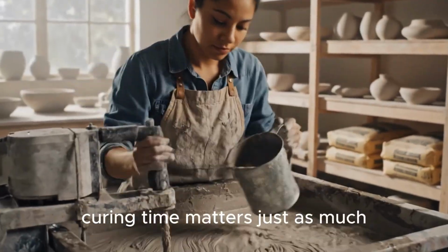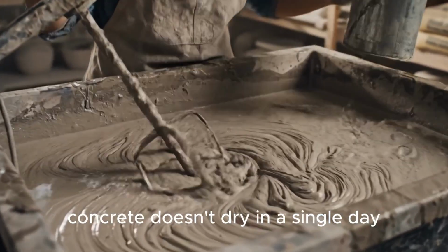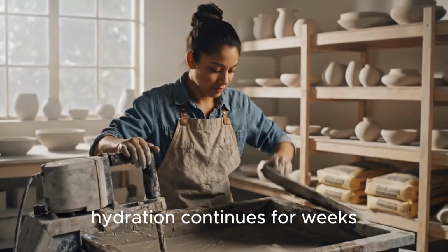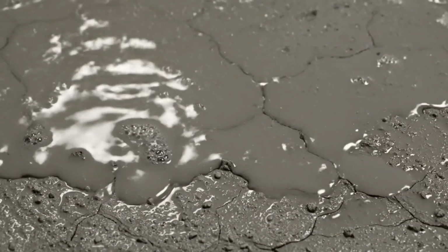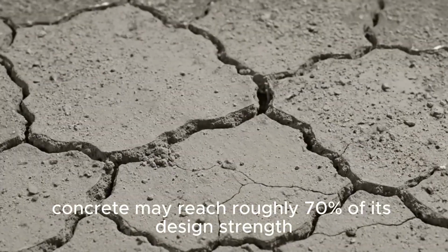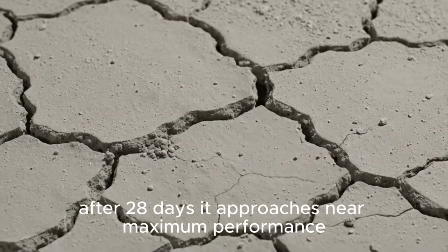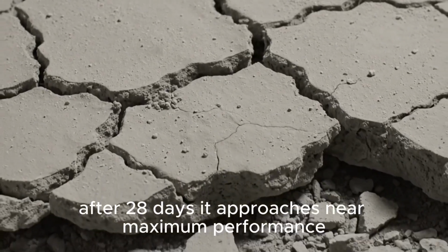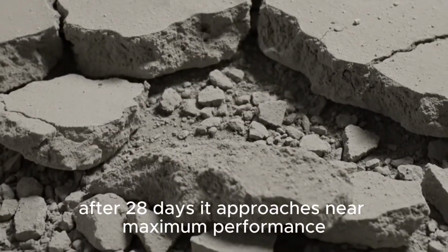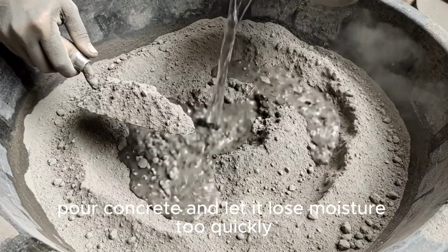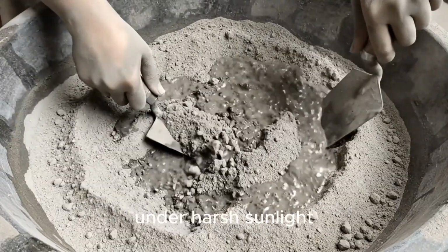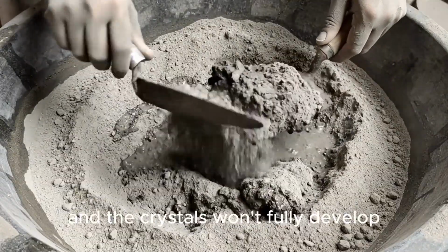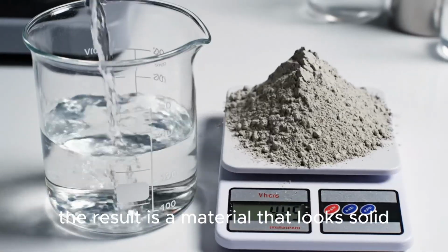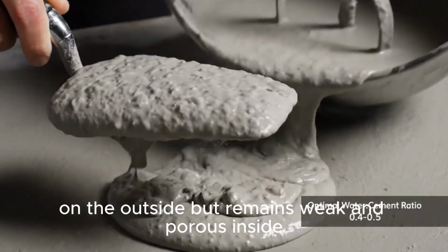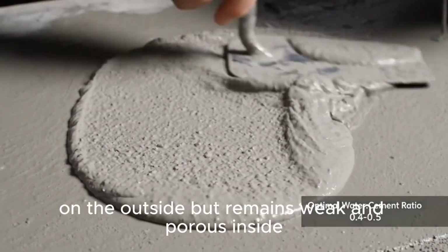Curing time matters just as much. Concrete doesn't dry in a single day. Hydration continues for weeks. Within the first 7 days, concrete may reach roughly 70% of its design strength. After 28 days, it approaches near maximum performance. Pour concrete and let it lose moisture too quickly under harsh sunlight, and the crystals won't fully develop. The result is a material that looks solid on the outside, but remains weak and porous inside.